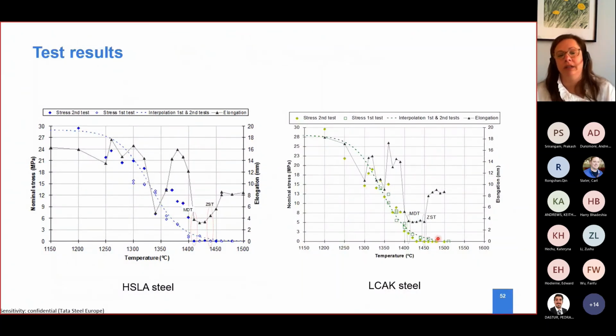What have we learned from these tests? Well, in this test we could follow the first ductility trough because it was so pure, there were no contaminants in it, so we could easily follow the first ductility trough. However, the collaboration unfortunately finished and we could not do more tests or more steels associated with that, so we left it there until another possibility came. We kept looking further and we went back to China, to the University of Science and Technology Beijing, USTB.